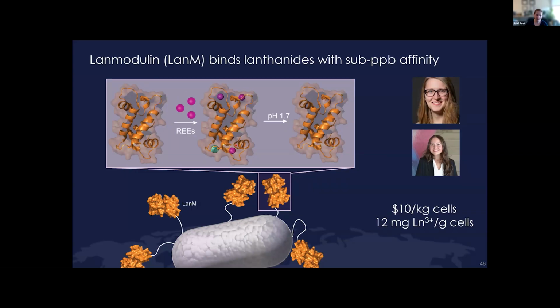We see them in the structure here. And this is actually a pretty poor representation of the structure because without the rare earths bound, this is actually very floppy and very inconsistent in terms of binding. I will note this work was done by a postdoc in my lab, Dr. Melanie Good, as well as an undergraduate, Tatum Willem, who's now at Stanford for her PhD. And I'll talk more about the technoeconomics later, but basically these cost us around $10 a kilogram for dried cells, and we get about 12 milligrams of lanthanide per gram of cells recovered.